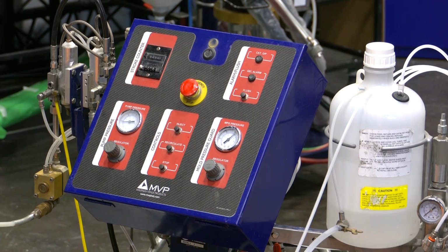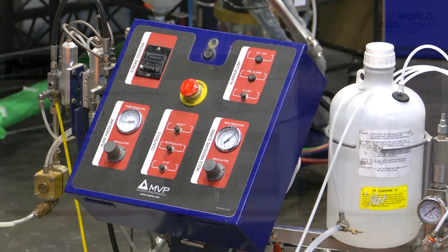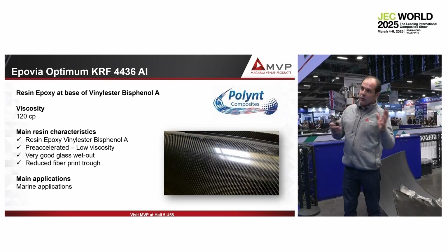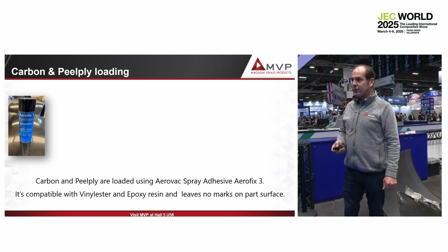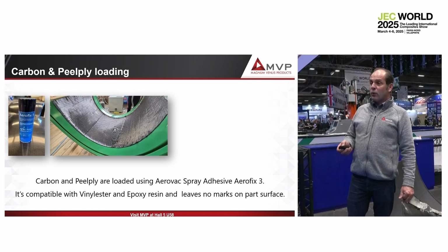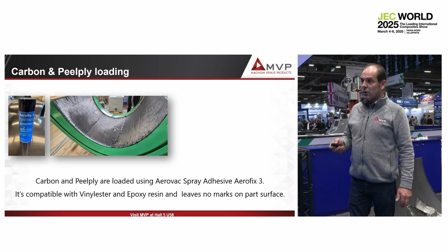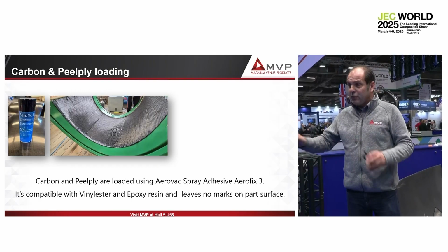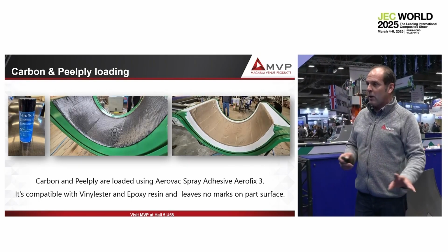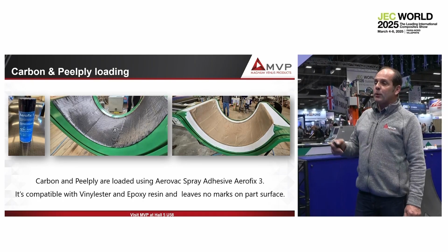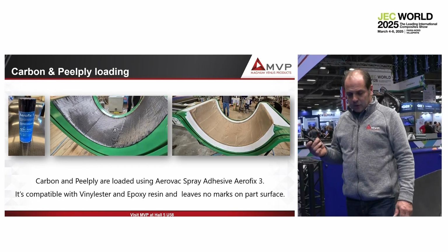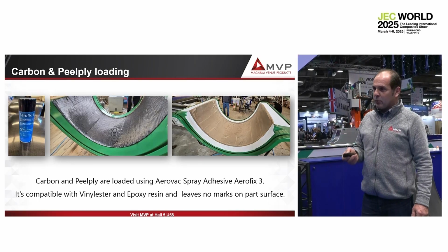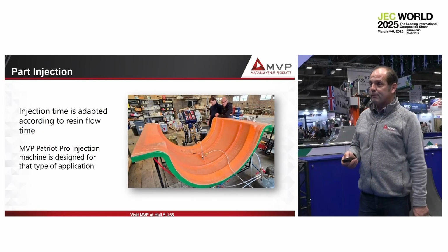So the resin we use is an Epovia Optimum KRF 4436AI from Polynt. A fantastic resin which is designed for boat builders. Normally the gel time is 2 hours, but they set up a gel time of 15 minutes for us, which is nice. We use different products from Aerovac to load the carbon on the part, and that adhesive completely disappears with the resin, so no mark on the part. And then on top of that, we put a special peel ply, which is Teflon-coated peel ply, very easy to remove.